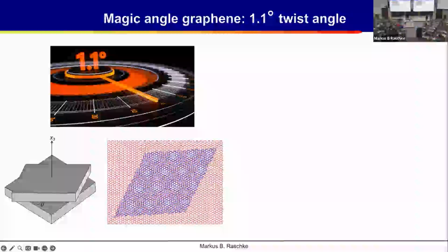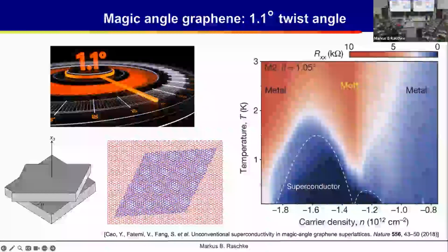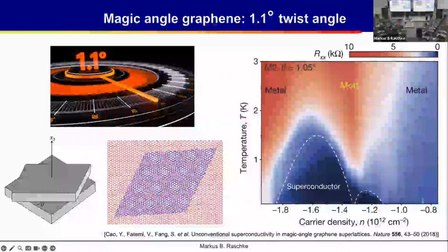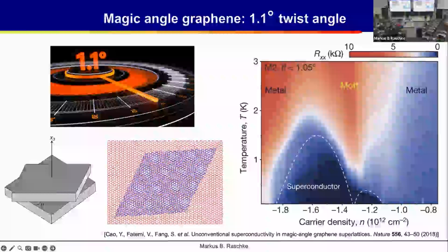Where this actually then itself allows the generation of new quantum states. And this has become an extremely rich laboratory, simply two sheets of carbon on top of each other with the right twist angle. You put electrodes on and you cool it, and then at a particular so-called magic angle, if you twist it 1.1 degree, then you form the right periodicity of the supercell in relation to the individual unit cell of graphene. And then at very low temperature, you actually get a superconducting phase.